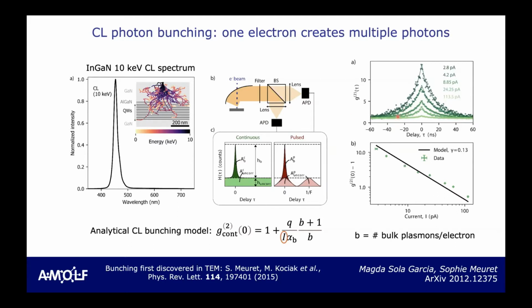So normally in incoherent light, this histogram is flat. You can have all kinds of time delays between photons, and the G2, that's this correlation function, is 1. But here you see it strongly peaks. It means photons like to come out at 0 delay or at longer delay. That's the lifetime basically of the emitter we're looking at.